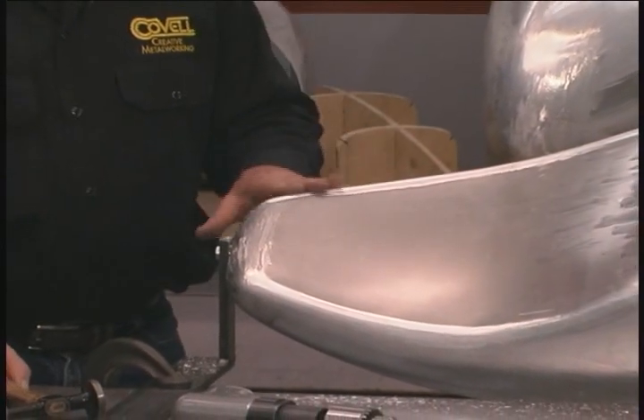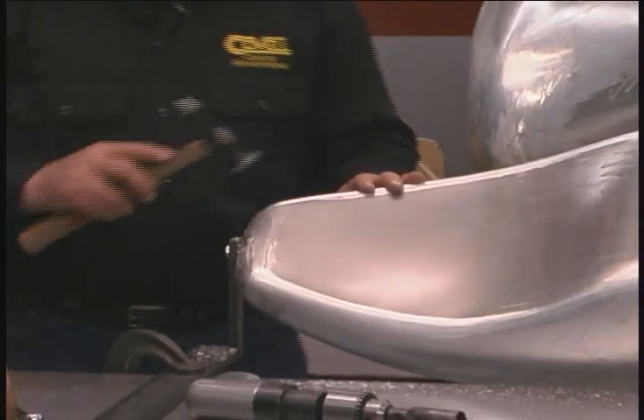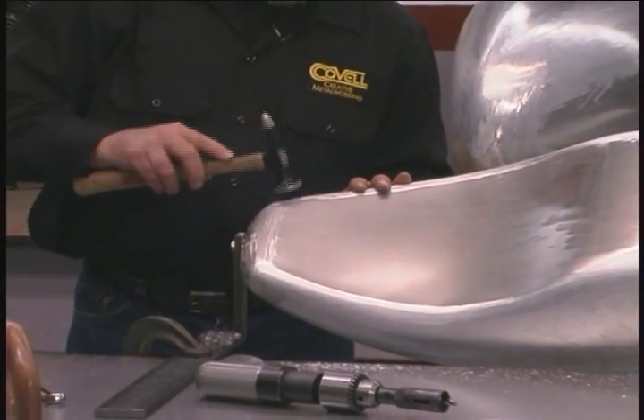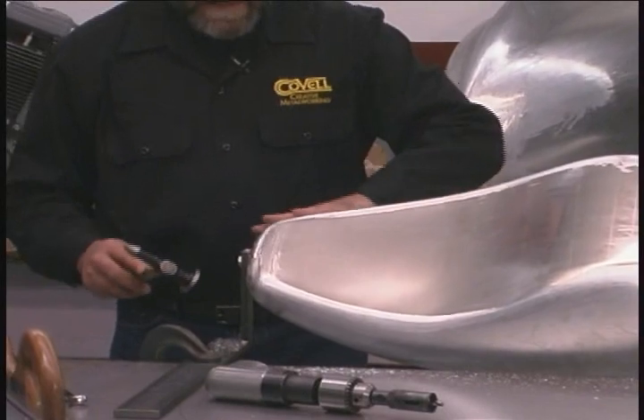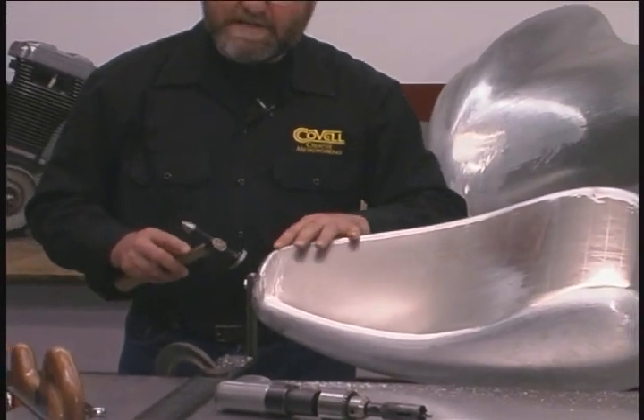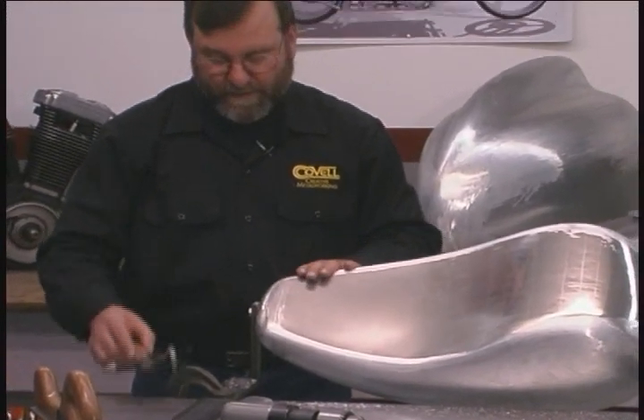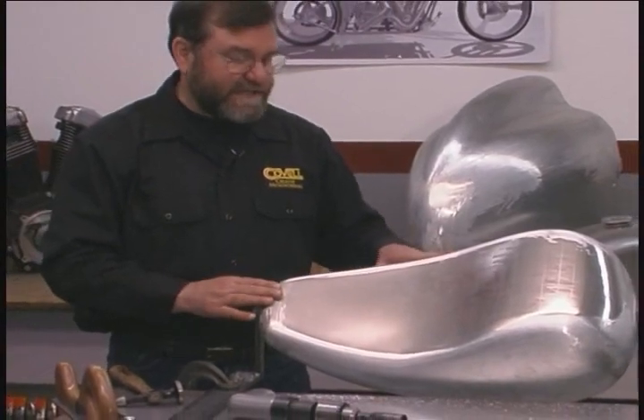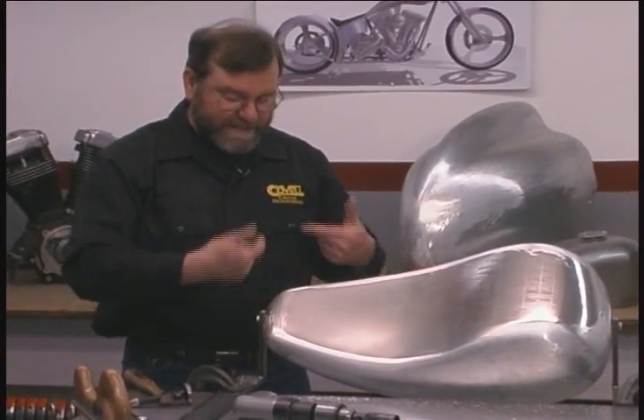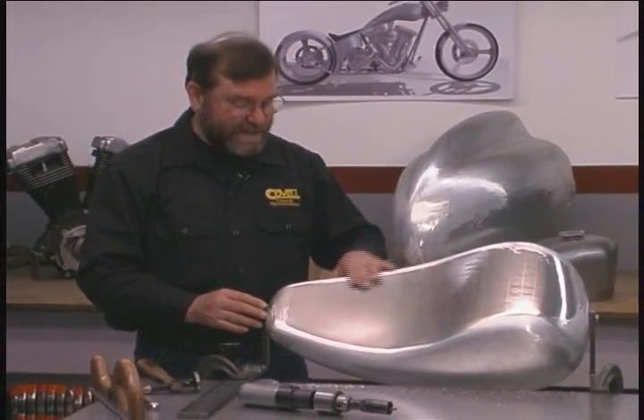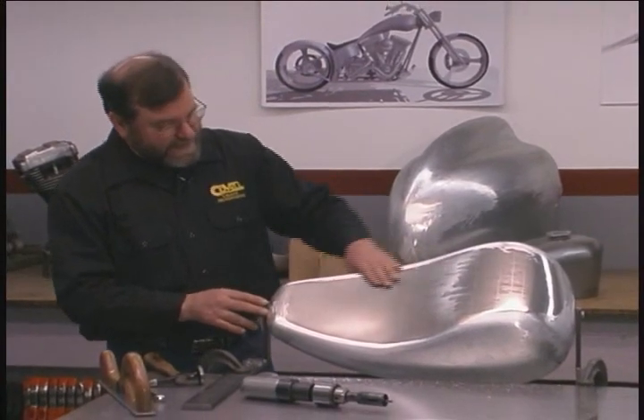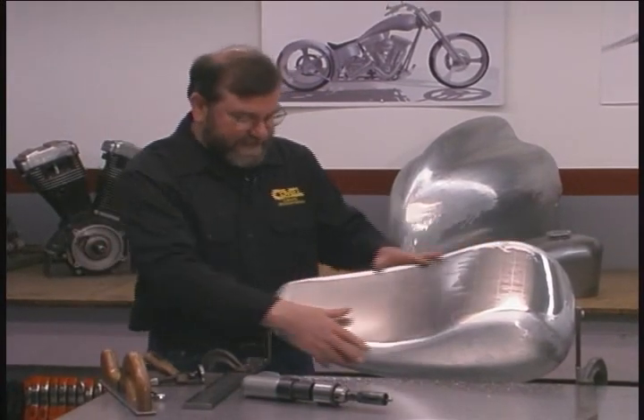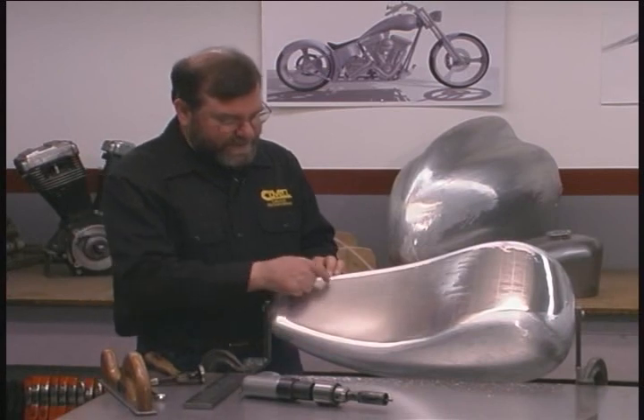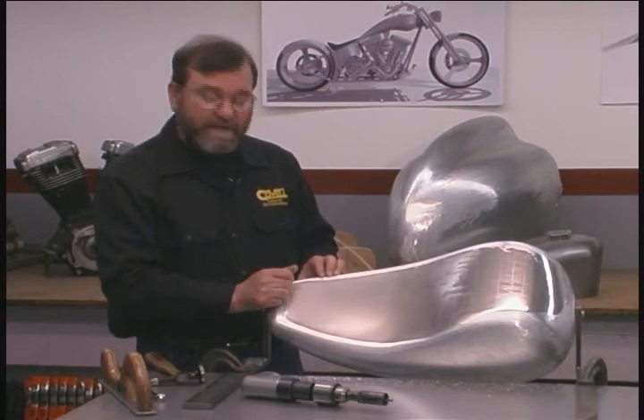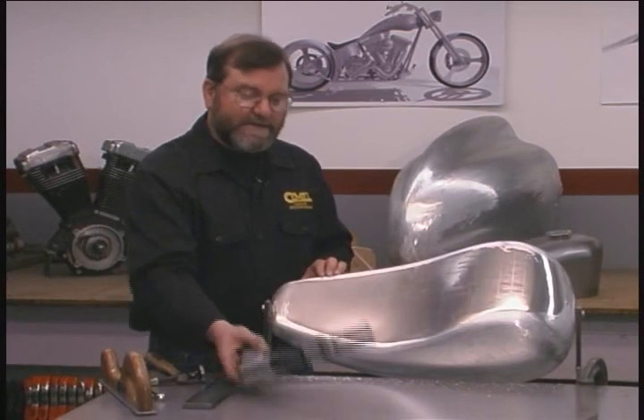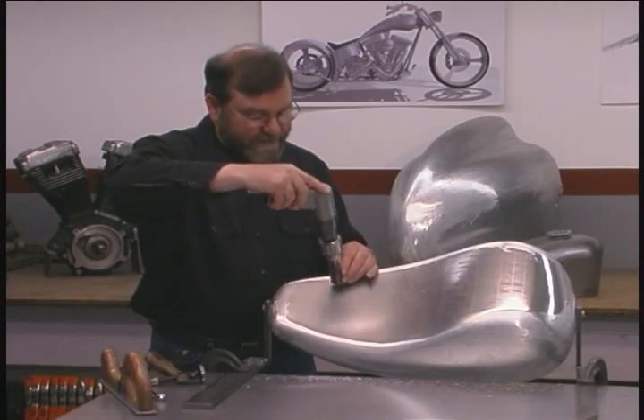If you find any high spots as you're doing this finish work, you can tap them down with a hammer. On highly crowned shapes like this, you can usually lower a high spot without any problem. If you find low spots, that's a little more difficult to deal with. We simply don't have any way to get inside to raise a low spot. Nevertheless, I think we've shaped the bottom of the tank pretty nicely. The next thing I'll do is to lay out the opening where we will put the petcock, and I'll use a 1-inch hole saw to create the hole for that.